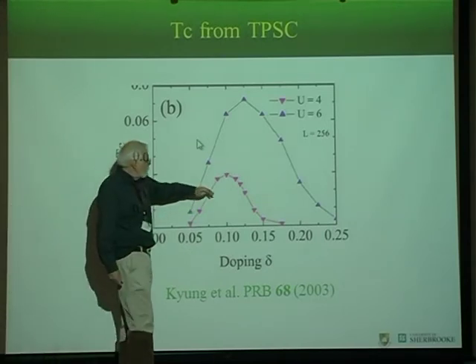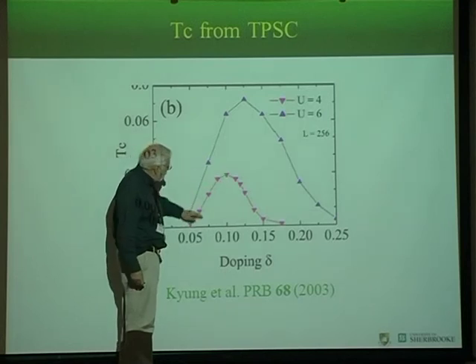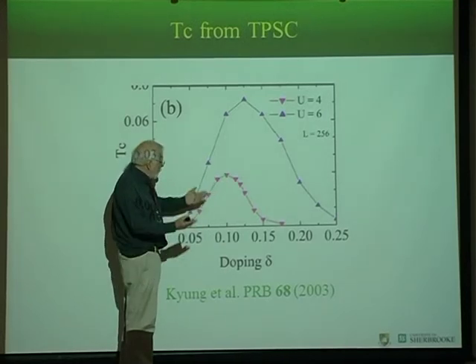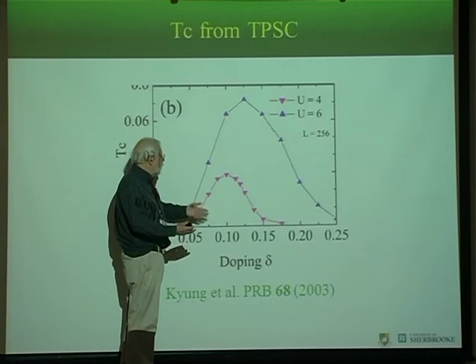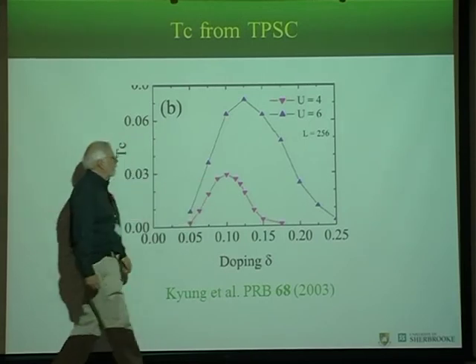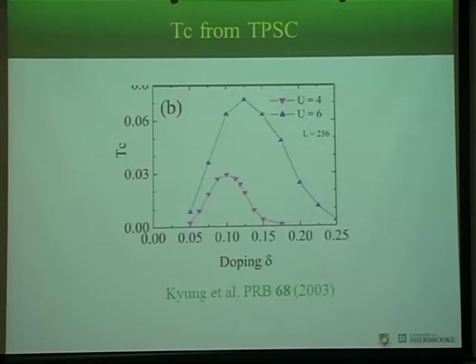And the reason for the dome is that in this region, a pseudogap comes in, so you remove states from the Fermi level, and then pairing becomes less efficient. So I would say that from the point of view of theory, much is understood in the case of this weak coupling point of view. I don't claim that there are detailed comparisons with experiment with electron doped, but it's sort of the next step to do.